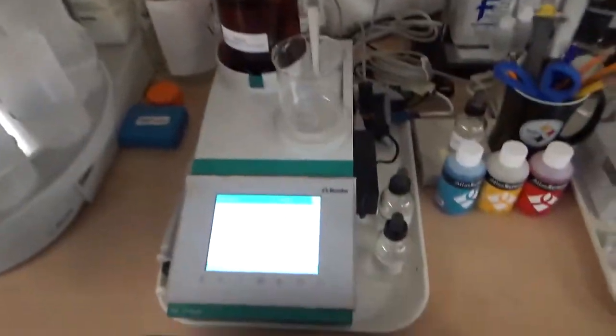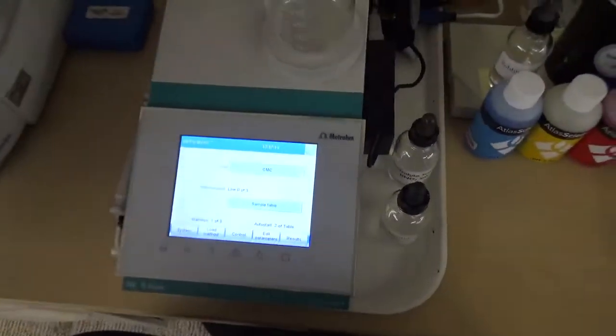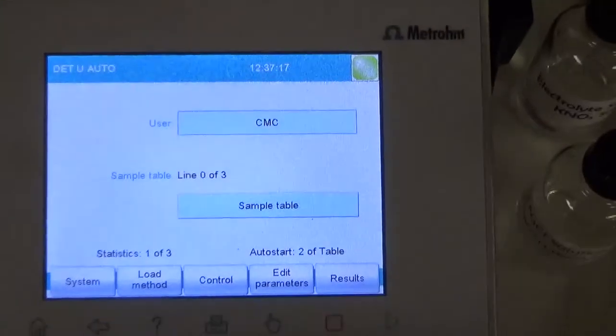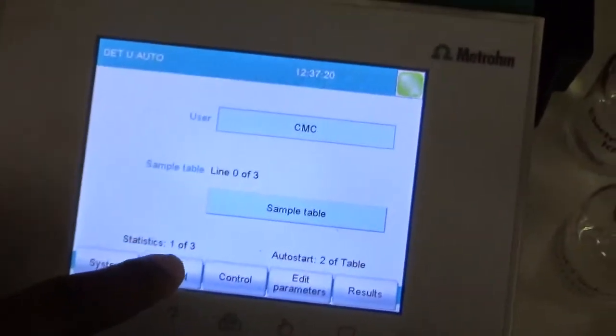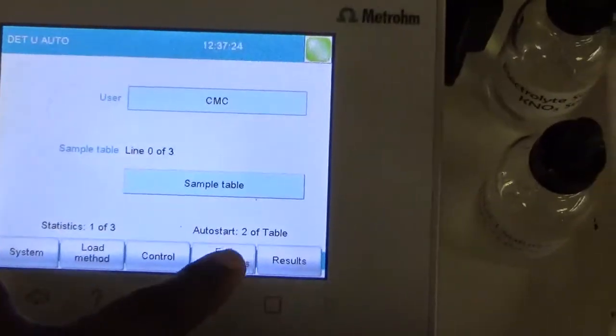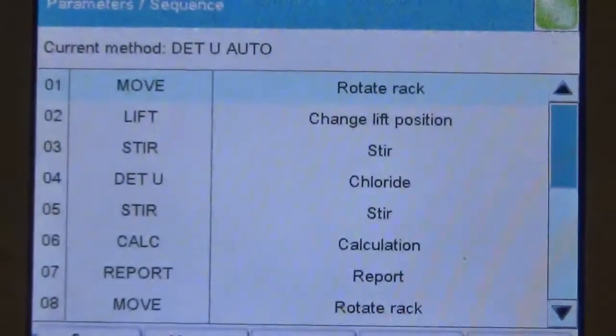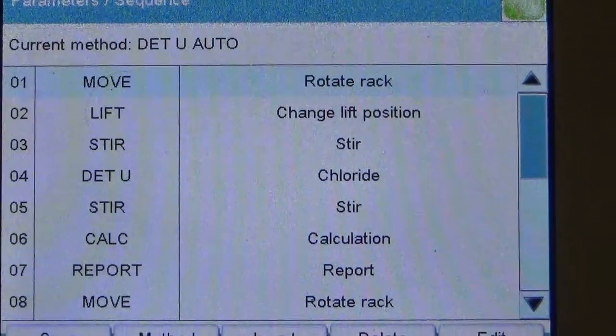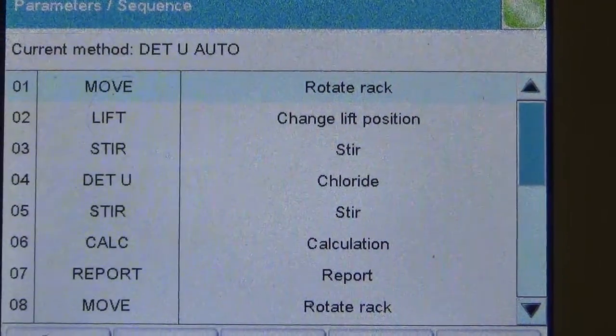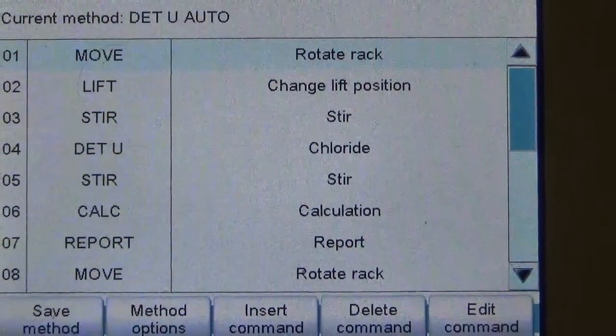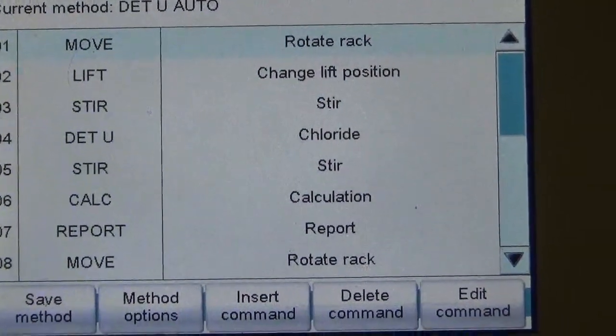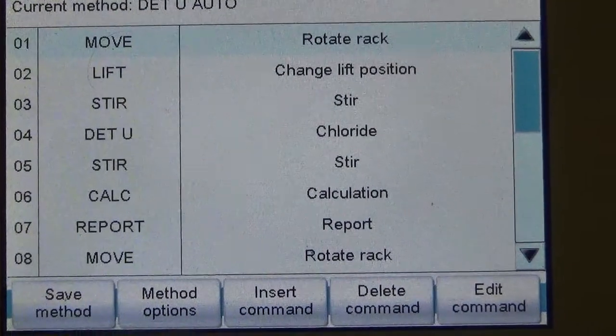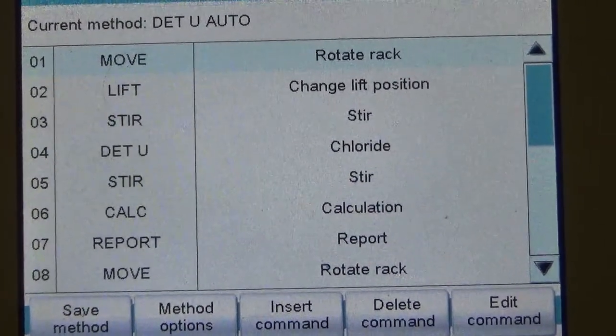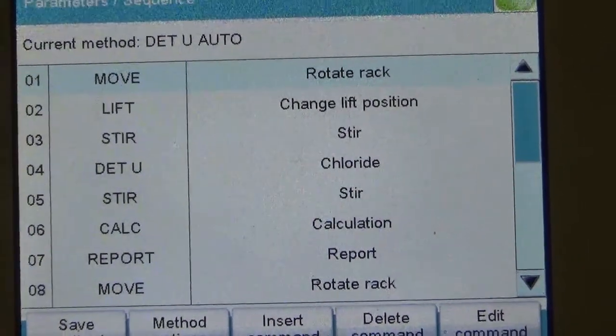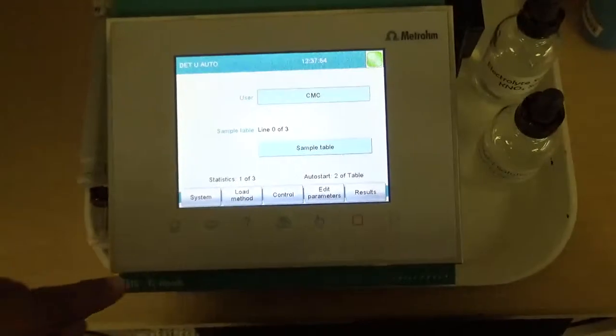So we set up a method to do the chloride titration, and we use potentiometric titration called DET U from Metrohm, where basically we load the method, and the method has a set of parameters which controls the titration. It moves the rack and lifts the column, does the stirring, then starts the titration, and while the titration runs it does the calculation for the chloride content, gives the report from the chloride titration, then moves to the next sample position. So this set of commands is already loaded under the method to do the titration.